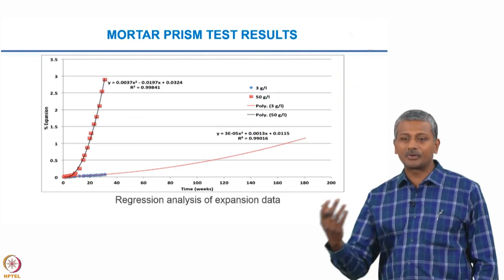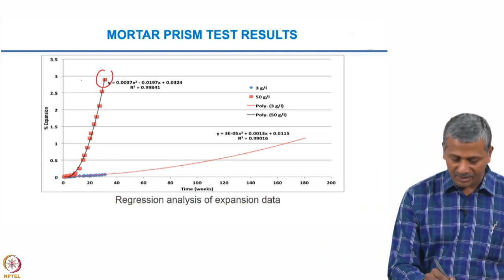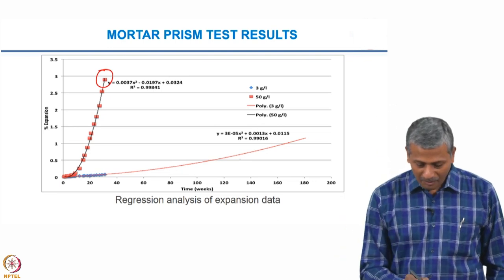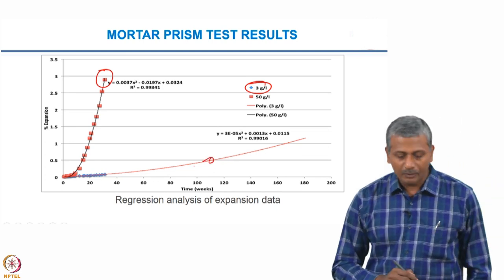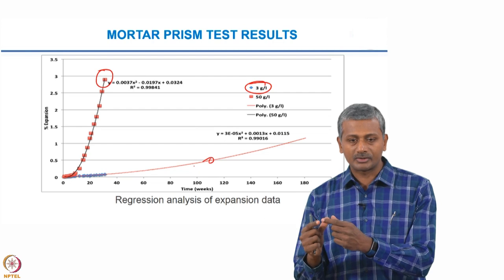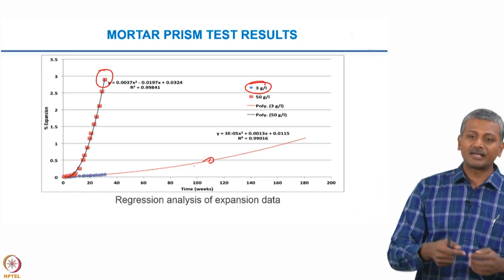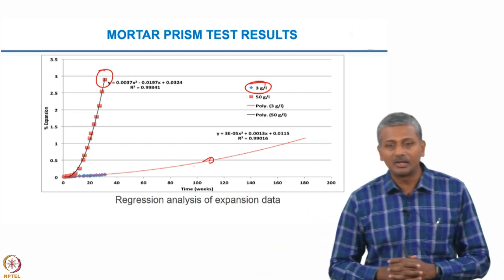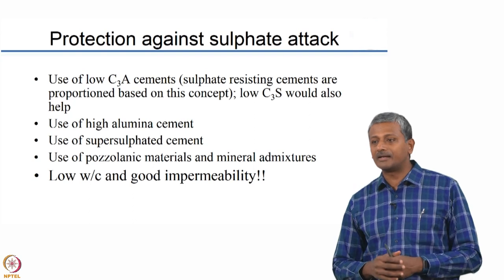Please remember these are small-scale prisms in laboratory conditions. In real life, much larger cross sections of concrete are involved, so the role of the surface skin expanding and resulting in such high levels of expansion is going to be minimal. In real life, the actual expansions seen in the field are going to be much lower than in laboratory conditions.